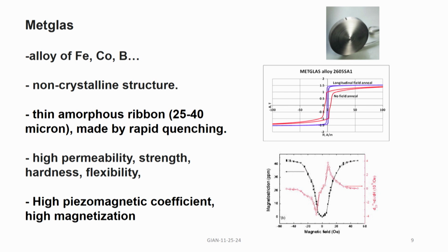So, whether you apply a positive field or negative magnetic field, it is always the same sense of change in the length, whereas the piezoelectric coefficient can switch from decrease in length to increase in length based on the polarity of the electric field. That does not happen in the case of magnetic field and magnetostriction. But there are materials called electrostrictive. For example, barium titanate is electrostrictive. PMN-PT is also electrostrictive. There it is either shrinking or elongation for both positive and negative electric field. PZT is piezoelectric, barium titanate and PMN-PT are electrostrictive. And in the case of magnetostriction, it is always either positive or negative. It does not matter whether you apply a positive magnetic field or a negative one.